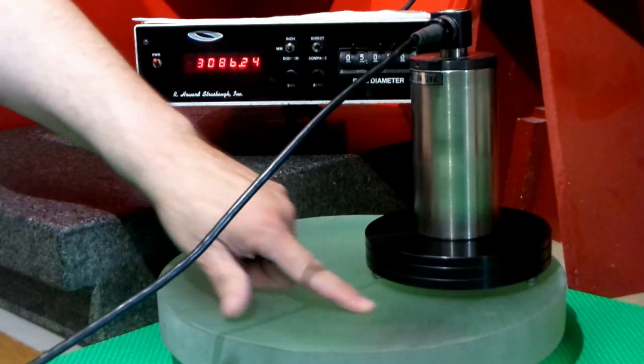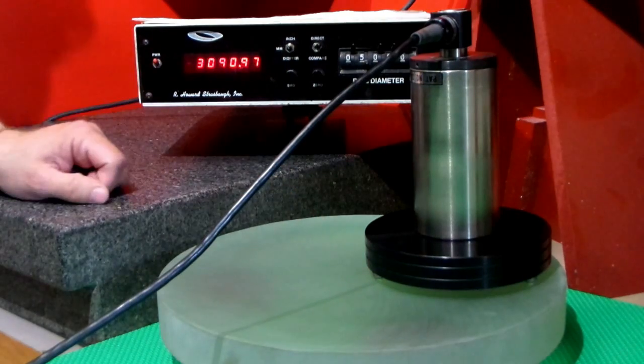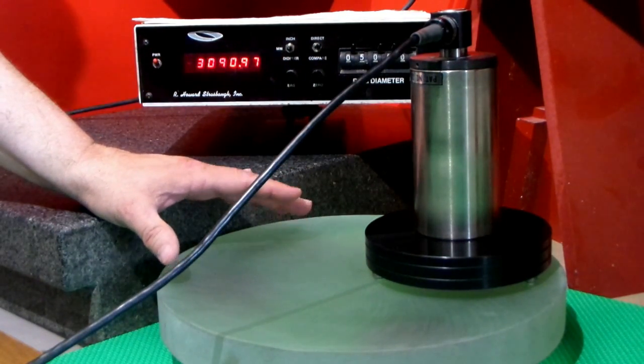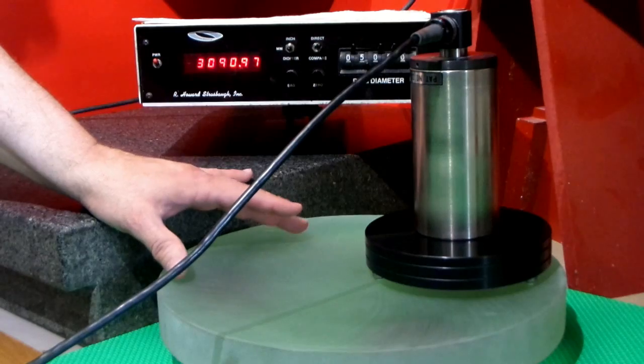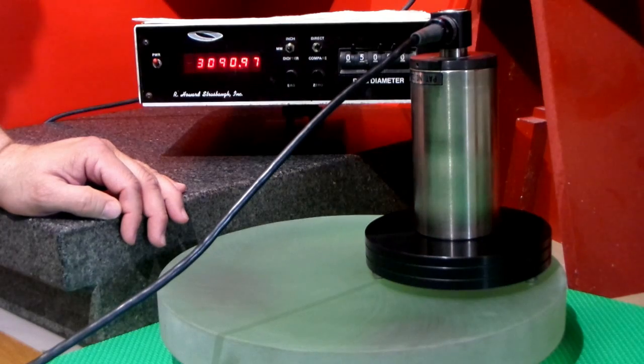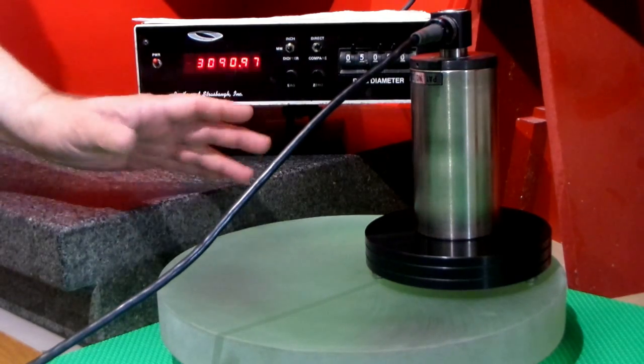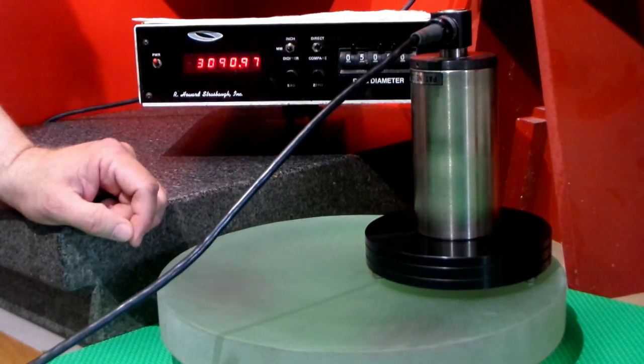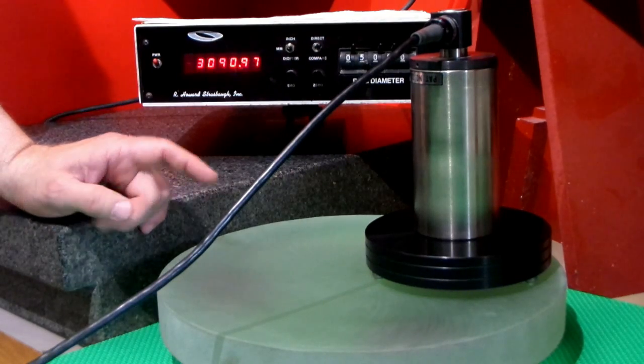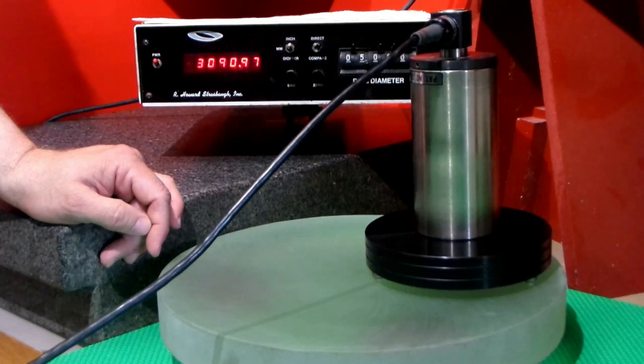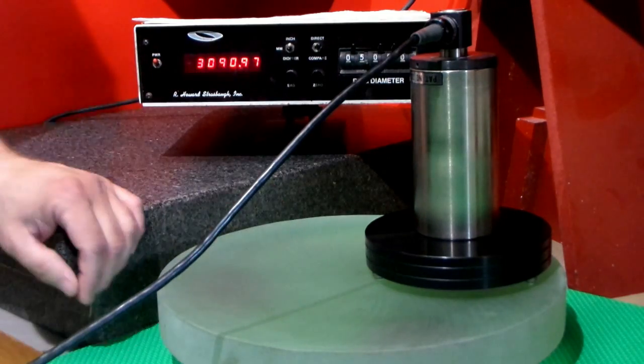Basically what that means is I'll be able to start my processing on this with 25 micron micro grit aluminum oxide abrasive. That really shortens up the time period that it'll take to do this mirror. So the spherometer says that the curve is really good. We're right on the 3,090 millimeter number, which gives us that 1,500 millimeter focal length. Basically everything checks out perfectly on this mirror blank. We're ready to make a grinding tool, a ceramic grinding tool, and start with the 25 micron on this particular mirror.